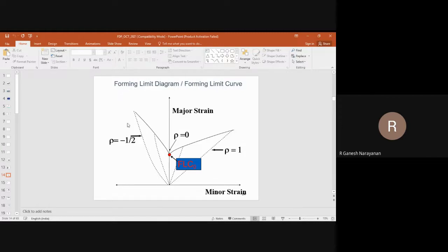So now the point here is this forming limit curve is also that kind of material property. If you don't do anything to the material, the forming limit curve generally does not change, like a stress strain behavior. And in a stress strain behavior, you have something called ductility. Ductility gives you some idea about the limit of useful deformation. We know uniform elongation, we know total elongation, correct. Uniform elongation corresponds to UTS, and total elongation is the final failure. These two quantities are generally used to quantify ductility. But generally total elongation is the ductility; we say 30% means you can deform the material up to 30%. And within that, you will get useful forming behavior, formability, or useful permanent shape change.